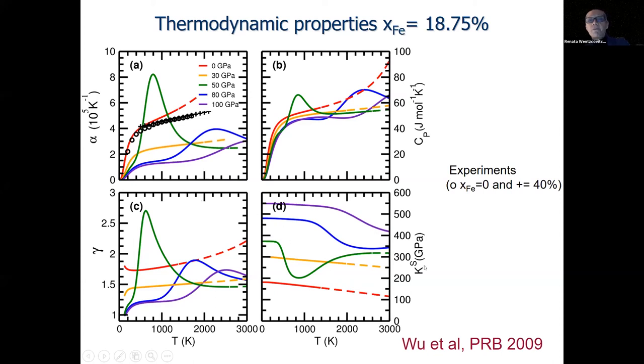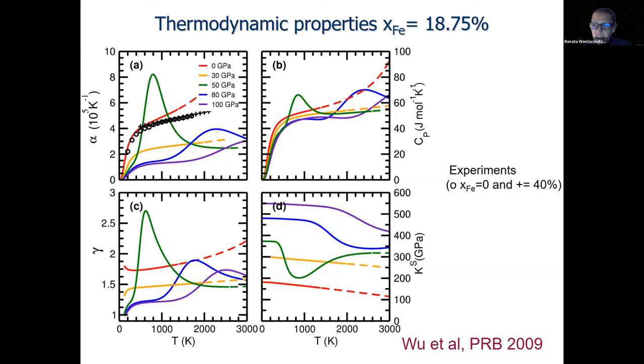This is very important to see what is happening with the bulk modulus at different pressures as a function of temperature. At 50 GPa, the bulk modulus decreases with increasing temperature as we go into the mixed spin region, and then it increases again. This is something very unusual — normally when you increase temperature, the elastic coefficients and bulk modulus decrease. But here the bulk modulus increases, which is very unexpected and has important consequences for seismology.